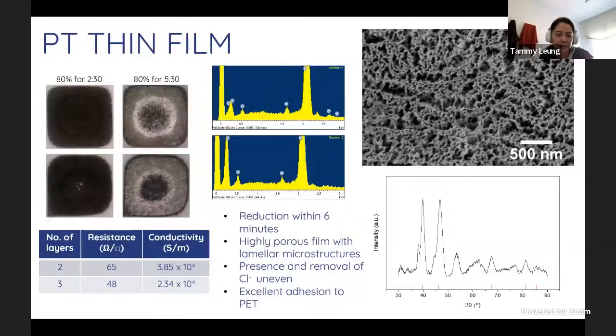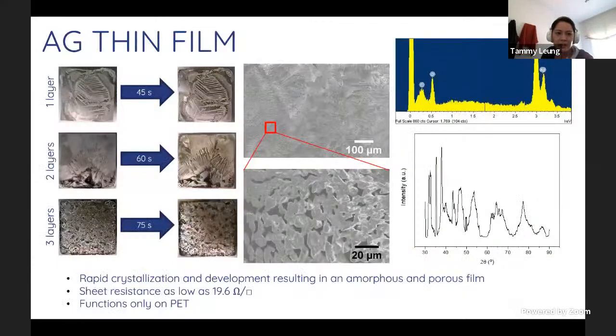And the reason for this circular pattern that you see in the fully developed films is that we discovered through EDX that there was still the presence of chlorine on the surface, which means that the plasma itself was removing the chlorine in different areas at different rates. So this is why you see sort of a circular pattern.